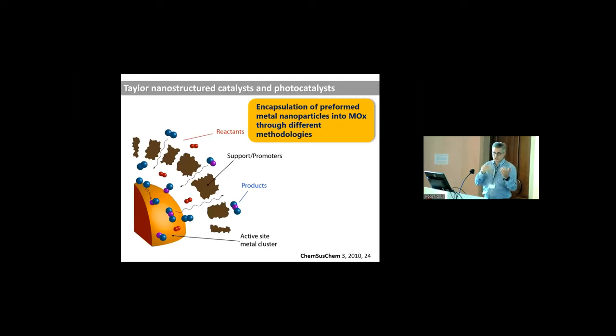I mentioned how important the metal support interface is. And so we were deeply involved for decades in defining a new strategy to make heterogeneous catalysts. Instead of supporting nanoparticles on preformed supports, we reversed the way to prepare the catalyst. So first making protected metal nanoparticles with different approaches, and then surrounding these metal nanoparticles by a porous oxide, an inorganic stable scaffold that prevents metal sintering, which is a common deactivation pathway in heterogeneous catalysis. And at the same time, we were able to maximize the metal support interface as shown in this cartoon. Porosity is extremely important to allow diffusion of reagents and products from the surface of the material.